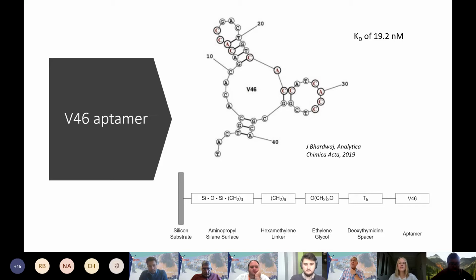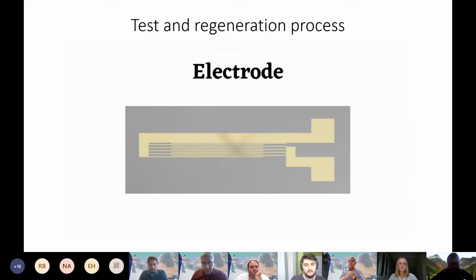A chain of functional groups initiated by aminopropyl silane covalently bonds the Aptamer to our substrate, as shown in the diagram. This carefully constructed chemistry of the cartridge ensures that the Aptamer has a greater binding rate and can withstand the recycling process. Now Jacob will take you through a step-by-step animation of the cartridge. Okay, this animation shows our testing and recycling process. Firstly, the sample is added, and it's left to incubate for 2 minutes. Next, a PBS wash removes the remaining sample from the electrode, after which the impedance reading is then taken.